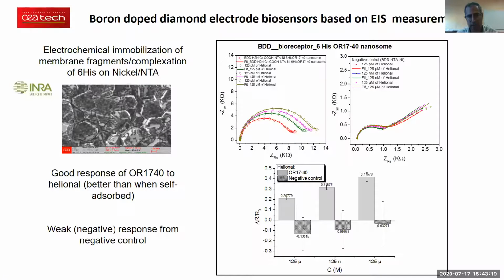So an example of this is this surface here, which has been functionalized with membrane fragments from yeast that contain an olfactory receptor. In this case, this is the human OR1740. And what we do again is we monitor the impedance of the electrode as we are exposing this electrode to different ligands. So this receptor is well known to have a high affinity with Helional, for instance.